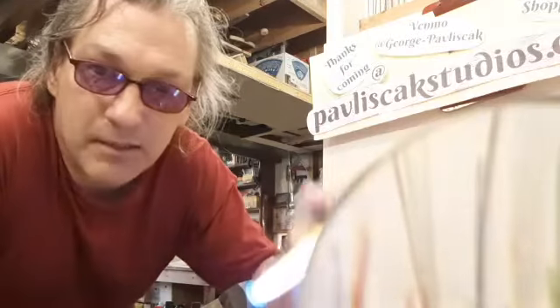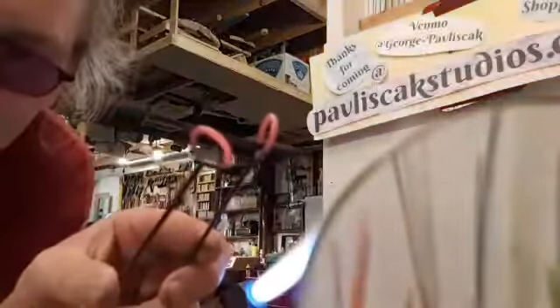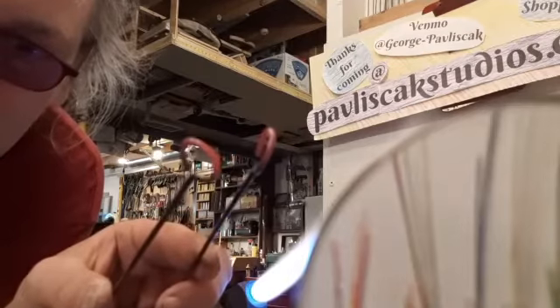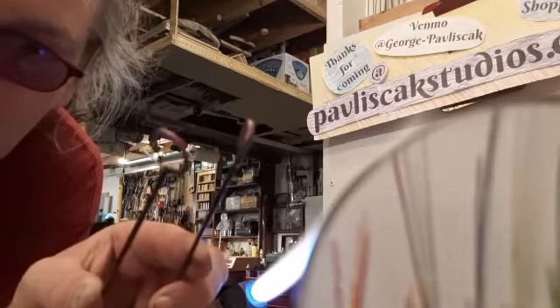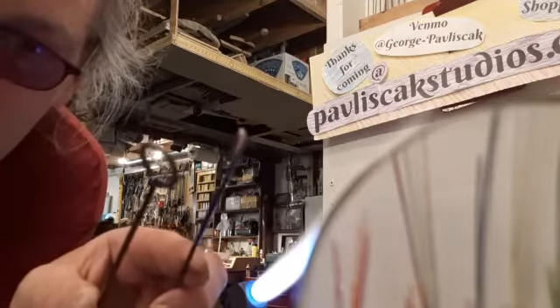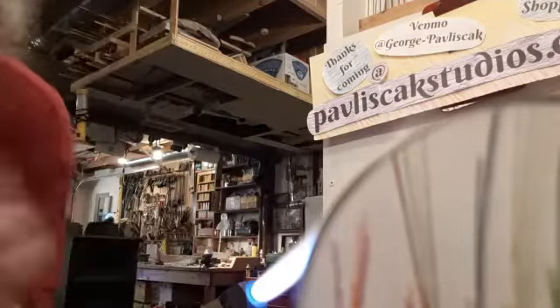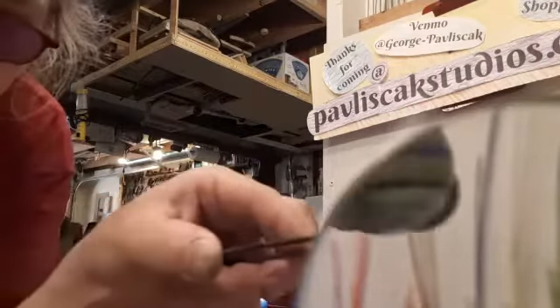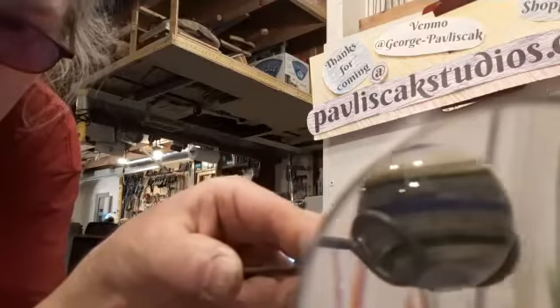Now I'm going to heat up these little tongs. I heat them up till they're orange. Then I let them cool down. It's like a lot of glass working. You sort of shoot above the temperature, and then as it's coming down, bam, that's the right temperature. I can go pick up my marble. I'm going to put it in the annealing oven.